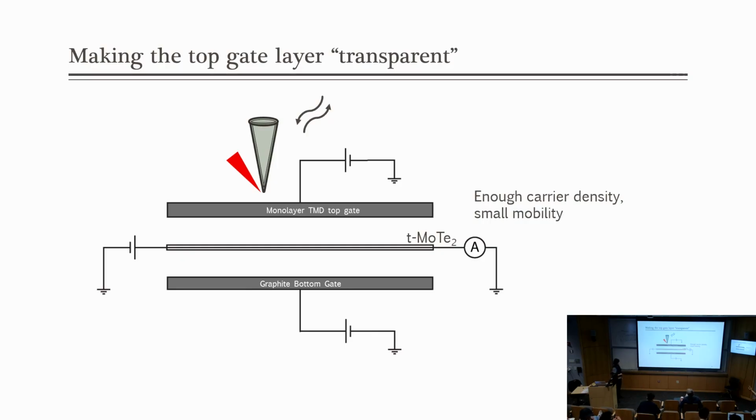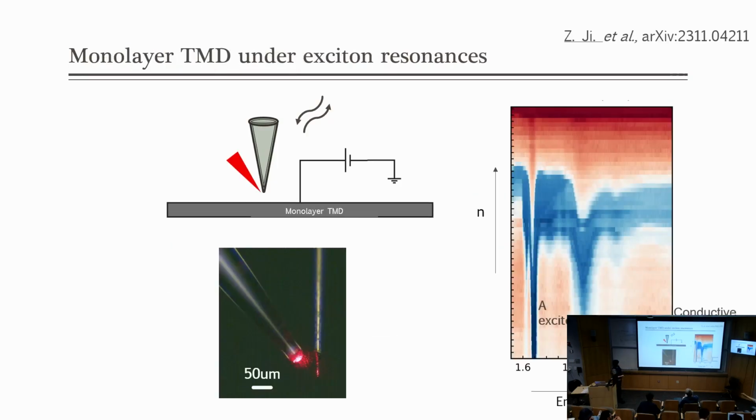But so you're utilizing this exciton peak, and you're cut off on the gate range. How much gate range do you have access to? That's a great question. This is only to a certain limit. To quantify it, I would say when it dopes to some prefactor times 10 to the 12th, it just became very conductive, and this gate stopped working.